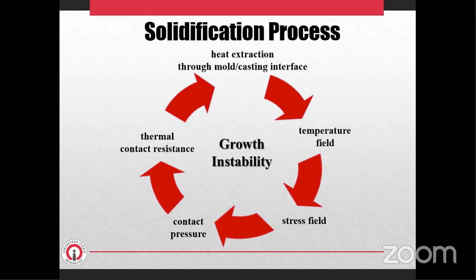Again, this affects the thermal contact resistance at this interface. As is seen, the thermal and mechanical problems must be investigated together, and the system behaves like a positive feedback system. Therefore, it may have the potential to be unstable. But in the uncoupled model, the contact pressure does not affect the thermal contact resistance because of the absence of the coupling effect.